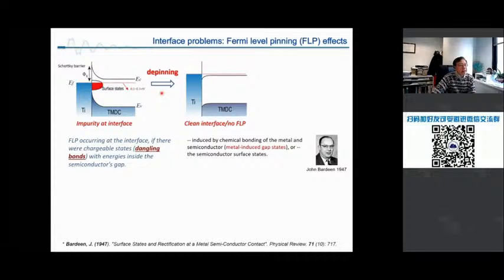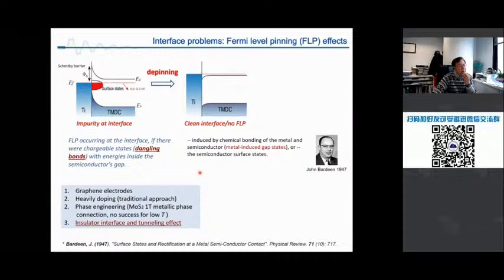So the way that you make ohmic contact is to make a depinning, to make a clean surface, to passivate these dangling bonds or charge traps, so that the work functions of the semiconductor and the actual metals can match each other, right? Match each other. So people thought about this for a long time and tried using graphene, for example, or heavily doped, the traditional method, or phase engineering, and so on. But the outcome is not that ideal. Still, the mobility is not high enough.